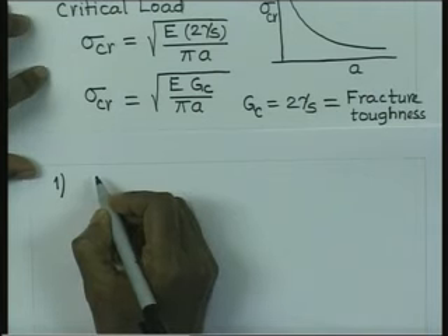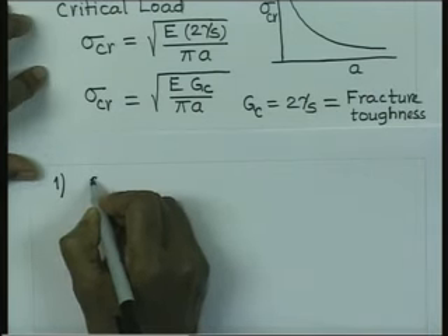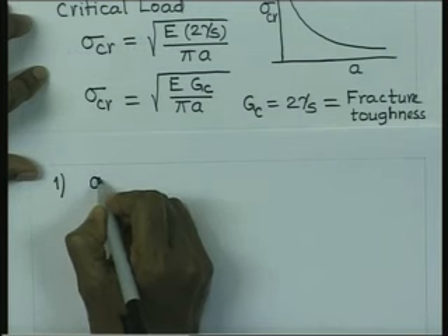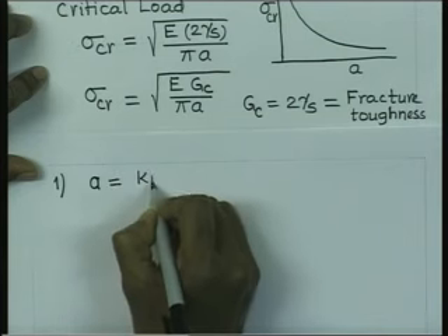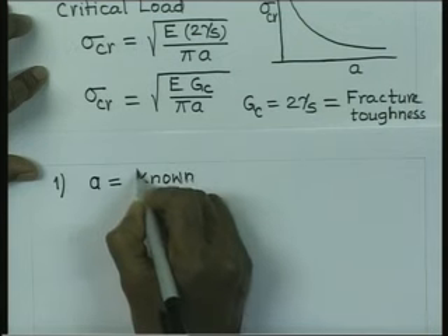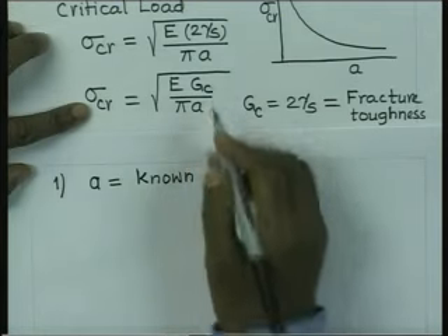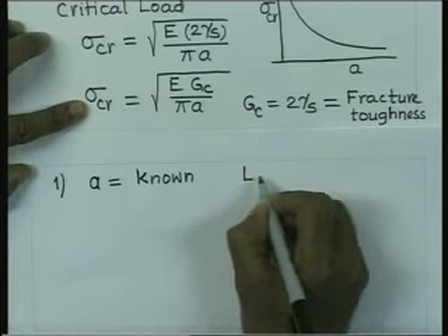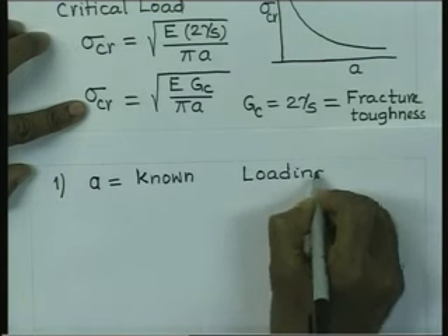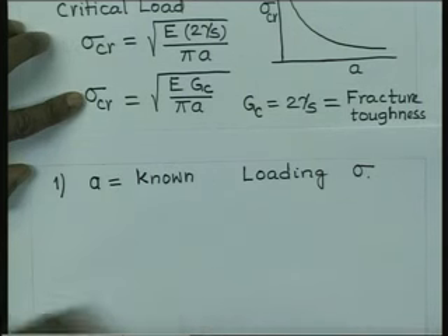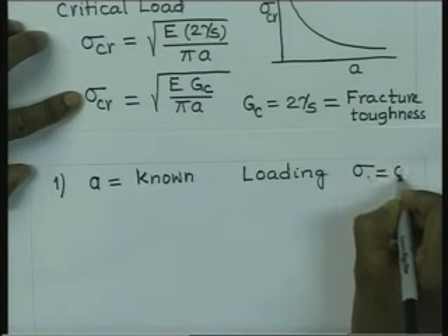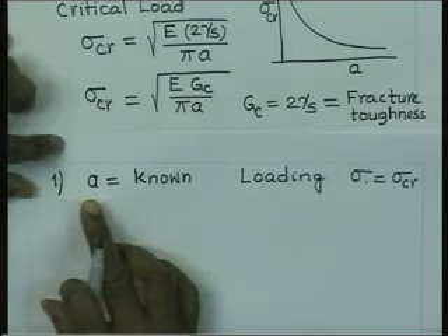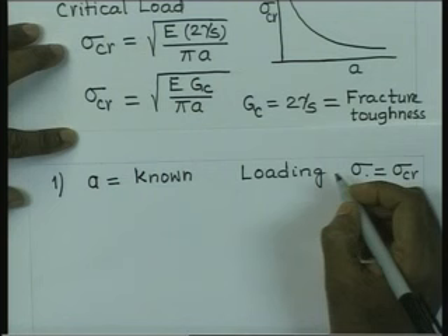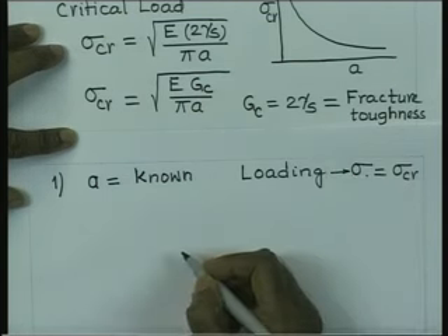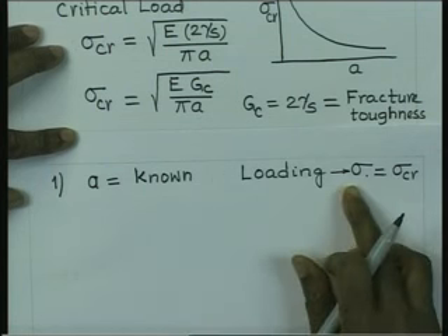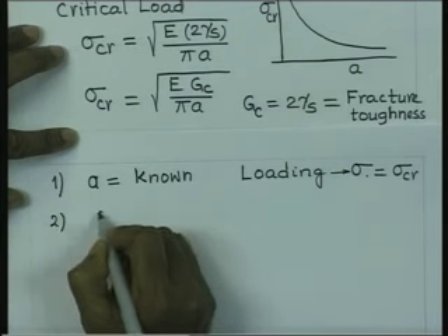So, if you are given the value of the loading, or if we consider a component with a known crack dimension a, then this relationship gives you what is the load capacity or what is the safe load, it gives you sigma. Let me put it this way: if we know the crack dimension in the component, then it is possible to calculate the loading which will trigger the crack extension, and therefore, one can ensure safety by keeping the load level below this level.